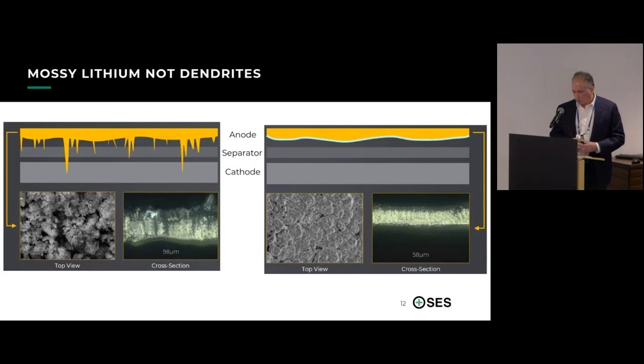So this is just a picture of the type of reaction that you get inside a battery cell. Our proprietary electrolyte effectively changes the morphology of what you'd find in a cell. Our CEO would call it, we get what's on the right, which is more of a mossy lithium, which isn't really dangerous to the health of the battery. What we have solved for is you don't want to get what's on the left side, which is a dendrite or a sharp needle-like structure that can form. And if it grows from the anode into the cathode, so pierces the separator into the cathode, you'd get a short in your battery.